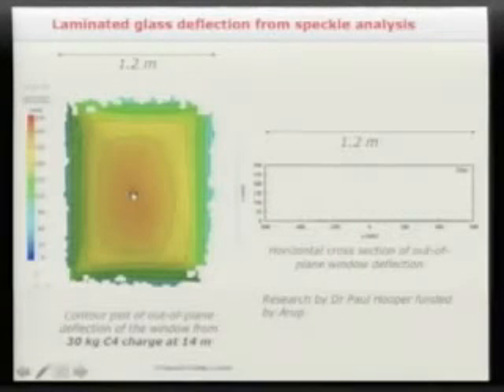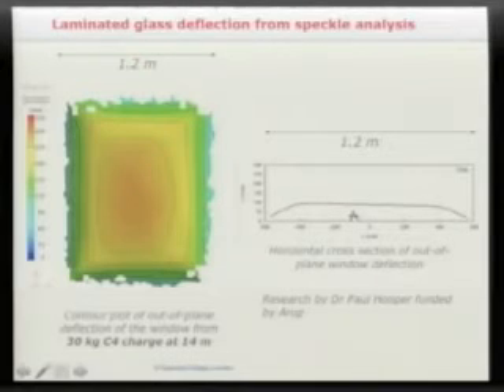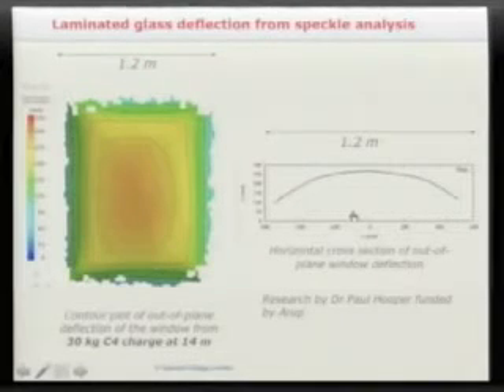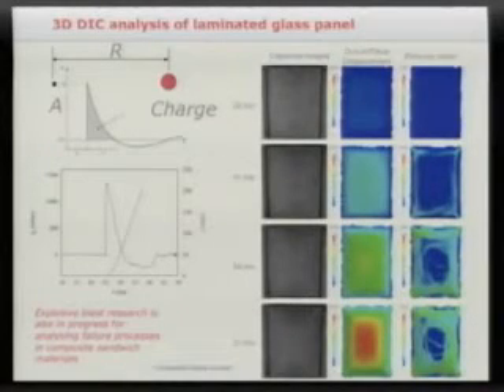And so you can see the center of the panel is fairly symmetric deformation, and it goes up to a deflection of about 270 millimeters there. And if you look side on here, you can see that the blast wave initially moves the laminated glass sheet, and then you build up the membrane stresses that builds up that parabolic shape. And so Paul can gather a lot of data for each test. He's got the DIC data here, and he's also got the pressure time trace here. This curve here shows the center point displacement. And so this is very useful data when you come to do FE analysis.